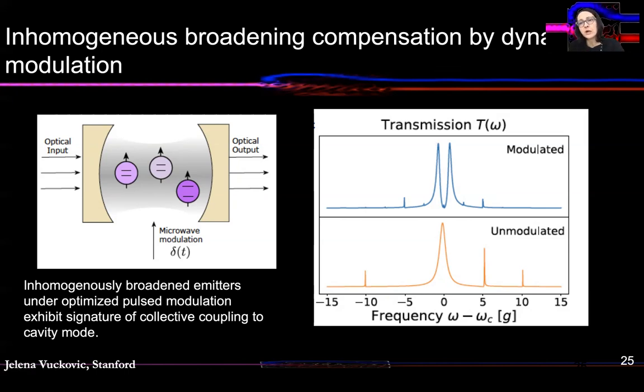And we are actively working in collaboration with the group of Ignacio Cirac in Munich on extending this to a large system of emitters, because in this case, the approach is very simple. You can build, let's say, a 100-atom simulator, even with inhomogeneously broadened emitters, just by applying a single set of electrodes on your structure to compensate for the broadening.